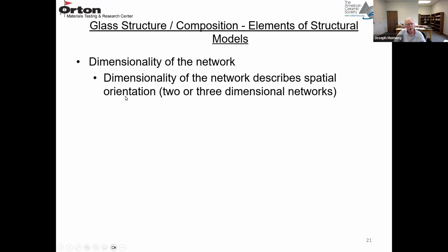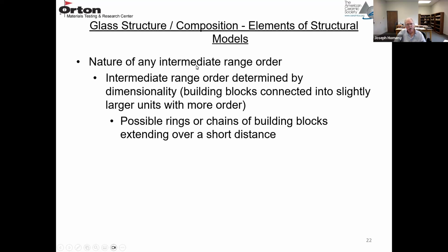So for the dimensionality of the network, it describes the spatial orientation. So 2 or 3 dimensional networks. It just depends on how the structural units are put together. And then the nature of any intermediate range order. So some of these building blocks can be connected to form slightly larger units. So the intermediate range order is determined by the dimensionality. So again, building blocks connected into slightly larger units with an additional amount of order. So they can form possible rings or chains, and these are the building blocks that extend over a short distance. So it's not long range order, but it is a little bit more order than just an individual building block or unit.